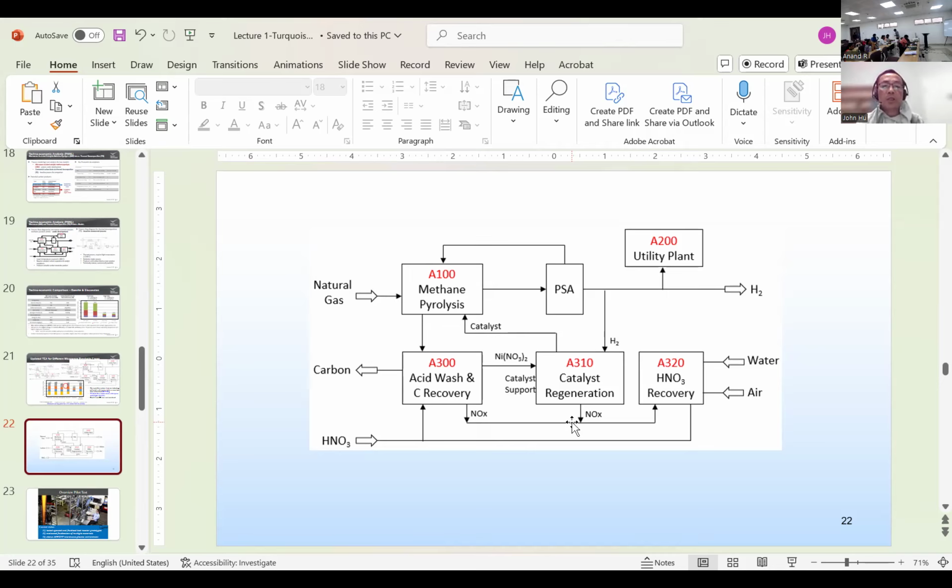In the laboratory, we just wash 3 times. We can get metal free. But in industry, it just depends on how efficient your process is. And by the way, that process needs heat because it's not just the wash. You need to dissolve. So that's why the hydrogen comes into the regeneration, and also you have to heat the process to make sure it effectively dissolves the metal.